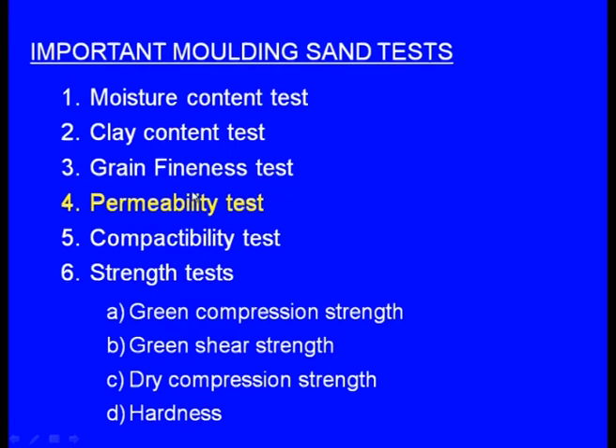Next, let us see the permeability test. Permeability is the ability of the molding sand to enable hot gases to pass through the neighboring sand grains and finally to the atmosphere. When we pour molten metal, the moisture in the molding sand reacts and forms steam and hot gases, which escape through the gaps between sand particles and leave the mold. If permeability is not adequate, the gases are accommodated inside the mold and lead to blow hole defects.